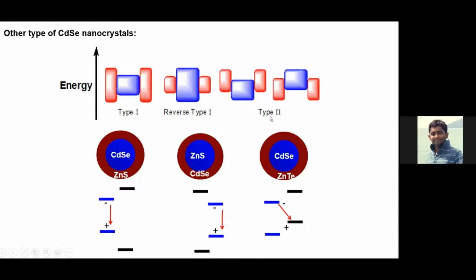And then the other is type 2. Type 2 means your bands are not covering each other, so they can align anywhere in the shell material. Like here you can see the core is cadmium selenide and the shell is zinc telluride. So the band gaps are not aligned with each other, so it can be up, it can be down. And when you shine the light, an electron-hole pair is generated here, and the electron transfers through from here to here. So you are shining here, but you will get an emission from the different structure. So these are type 2.